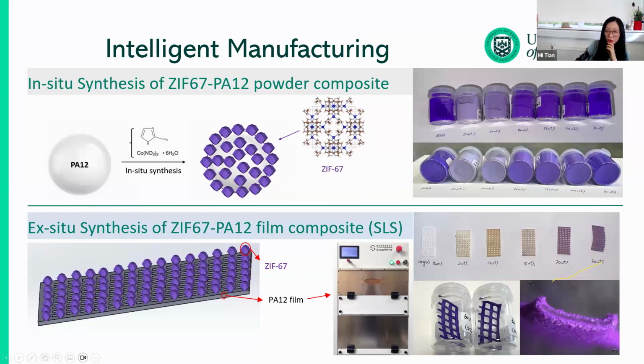And then, of course, you can control the shape, whatever shape you want. In ex-situ synthesis, we print the shape out using polymer, and then we grow the MOFs on the synthesized film. It's not only film, because that's a bit simple, but it also can be different shapes, different cages we are testing. So this is a fascinating area and really bridges the lab technology and industry applications.